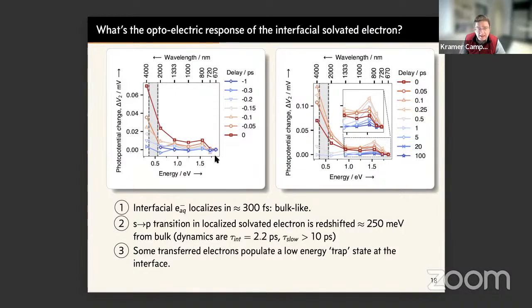And each of these curves now are at a different delay point. So you can see at -1 picosecond, so that's now where the resonant probing pulse comes before the UV by a picosecond, there is no 2-photon photovoltage signal. That's the dark blue line. But as you approach 0, you gain a lot of signal at long infrared wavelengths, right? So we went as long as 4,000 nanometers, but whatever this feature is, it's clearly peaked way off at long wavelengths.